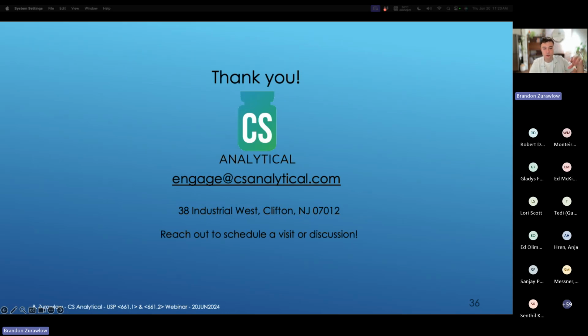Like I mentioned, you have the material from which those different size bottles are created qualified by 661.1, and then perhaps the smallest and largest bottle, which theoretically should represent the highest surface area to volume ratio and the lowest surface area to volume ratio, to bracket and say worst case, best case. On the final containers, here are my results. And by the way, all of the materials that we're making these containers from are qualified across the board. But that is something that we would typically evaluate relative to the material.